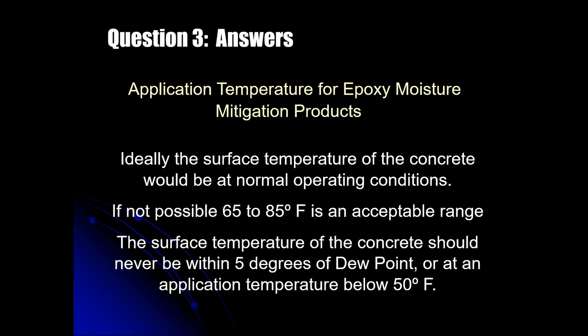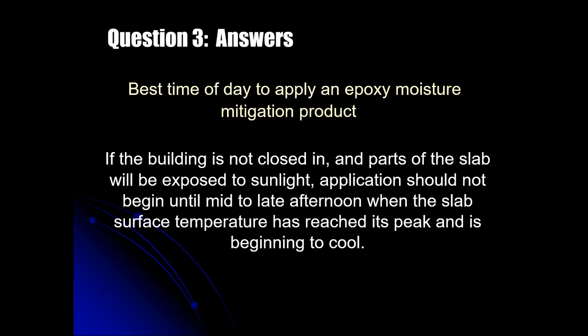Historically, you'll find in the coatings industry that they do not want you to install a coating when the surface temperature of the concrete is within 5 degrees of the dew point. I've seen some more recent publications that suggest it should not be within 10 degrees, and I think part of that has to do with just the accuracy of the instrumentation that we're measuring these temperatures with. But whether it's 5 or 10, there needs to be a definite difference to not put the application at risk of a dew point condensation issue.